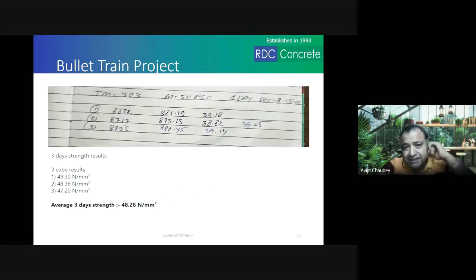Now some case studies. This is the bullet train project trial that we did. Their requirement was M50 for pre-stressed concrete, and in one day for M50 grade concrete, they have been able to get 39.05 MPa with our ultrafine minerals. At 3 days for M50 grade, they have got an average of 48.28 MPa, right? Which was much less as compared to the microsilica that they were using earlier.